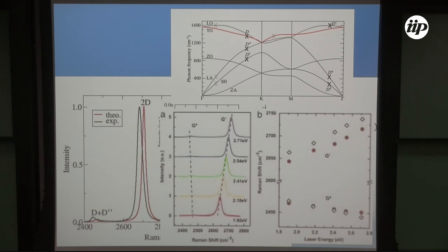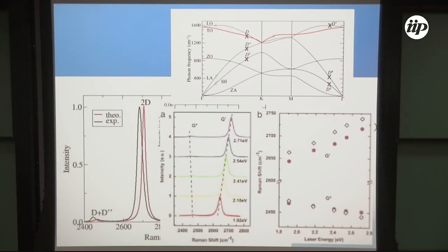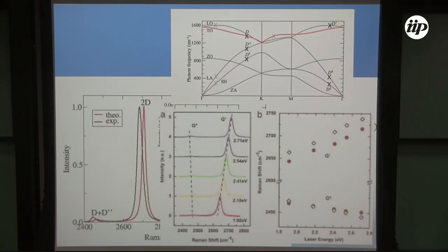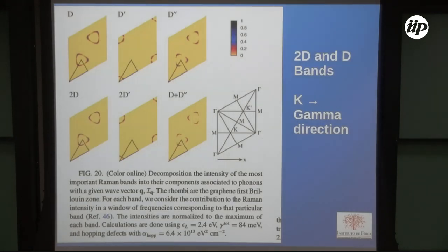So what's nice about double resonance is that now you can measure things that are far from the gamma point in some cases. Here, the first-order process only measures this phonon. With a double resonance, I can measure several phonons in those branches here. So we have more possibilities with this kind of process. Also, we can look exactly at what the phonons are that take part in the process.